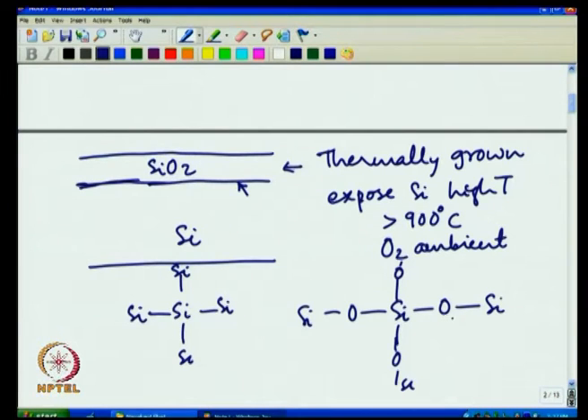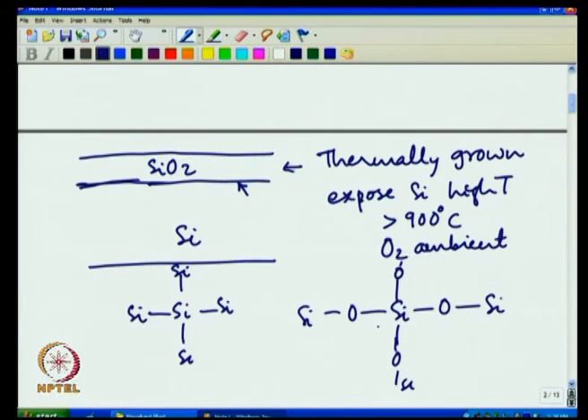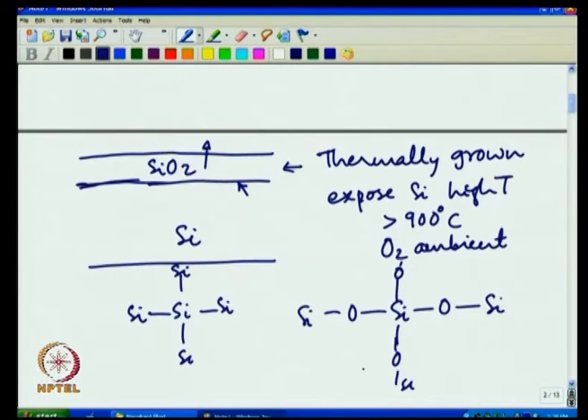An oxygen atom is shared between two silicon atoms, which satisfies the valence. Hence a silicon atom is bonded with four half-oxygen atoms, which is essentially SiO2. This is not crystalline — it is not very regular — but every silicon atom will bond to an oxygen atom. This is the structure in bulk silicon oxide: as oxide grows deeper, you see a very ideal silicon oxide structure where silicon is bonded to oxygen, which is in turn bonded to silicon.